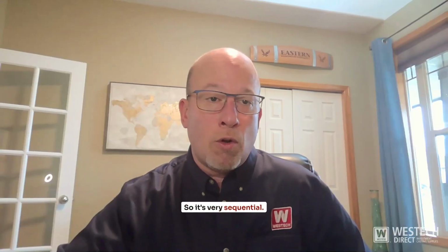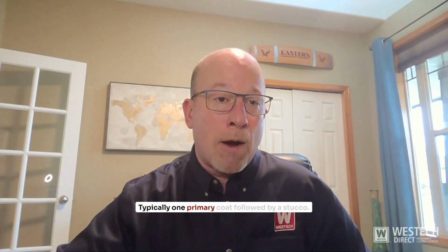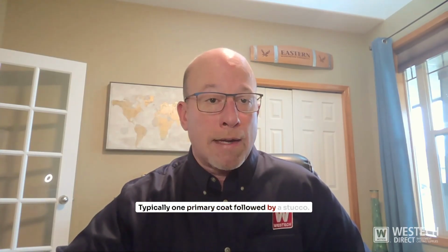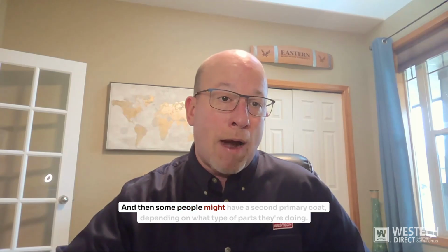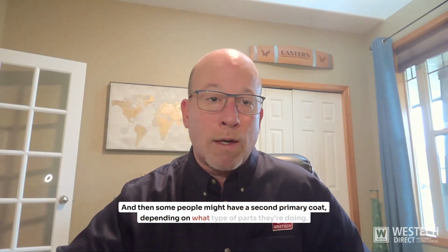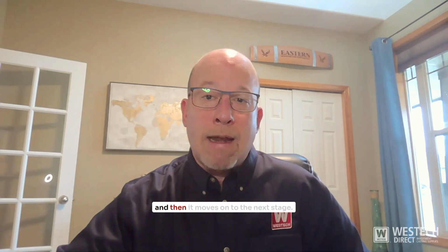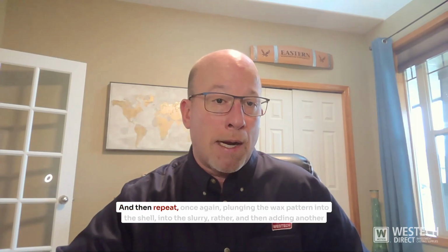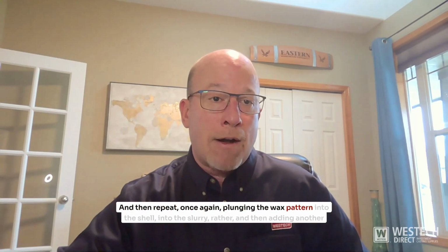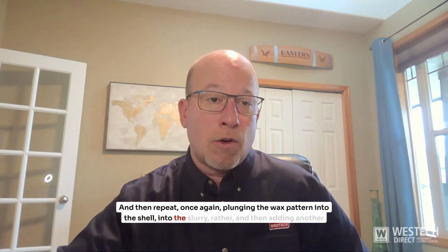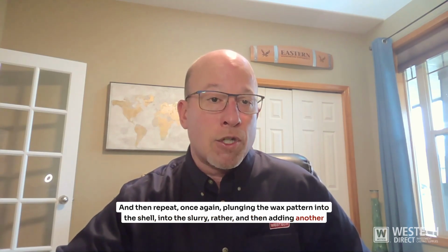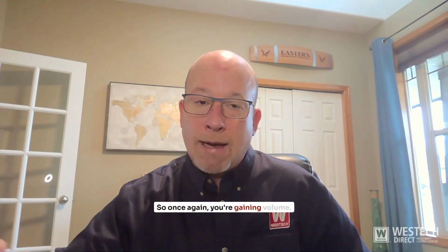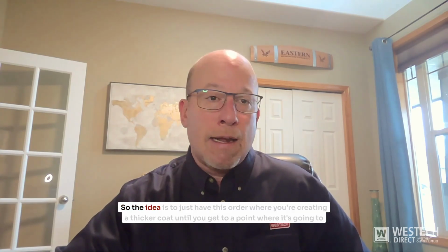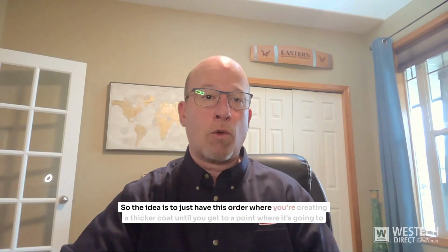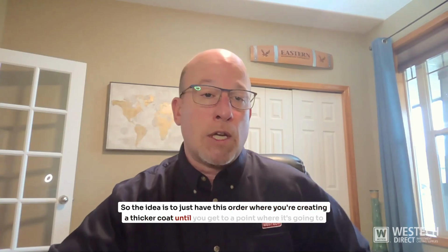So it's very sequential, typically one primary coat, followed by a stucco. And then some people might have a second primary coat depending on what type of parts they're doing. And then it moves on to the next stage and then repeat. Once again, plunging the wax pattern into the slurry, and then adding another stucco coat. So once again, you're gaining volume. So the idea is to have this order where you're creating a thicker coat until you get to a point where it's going to be able to withstand the process.